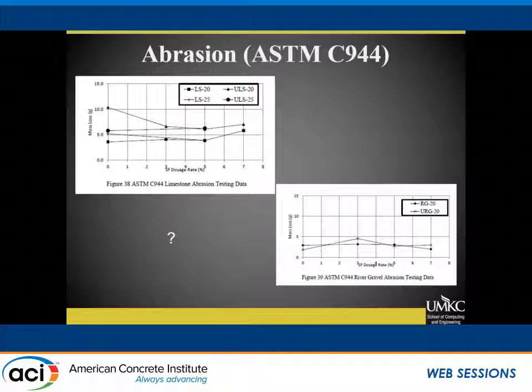on the surface, and we didn't see anything. So we had our unwashed limestone, we had a decrease in abrasion between 0 and 3%, and then everything else in the study, there was no difference in that surface abrasion. And then this is our river gravel samples, and our river gravel samples we also didn't see any difference. So got a question mark there.